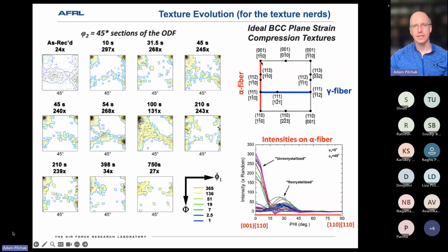And so if I now plot just the intensities starting from this rotated cube orientation toward the 110 type orientation over here, I can see a distinct transition where I initially have really high intensities in the unrecrystallized state. As annealing time increases, we start seeing a decrease in that intensity, and an increase in the intensity in these recrystallized regions here. So there's this transition or flow of orientations that mirrors what we looked at on the last slide. Hopefully that's not too surprising.